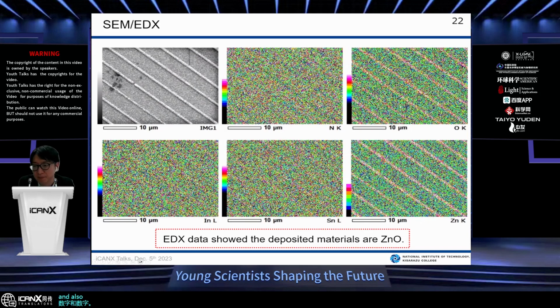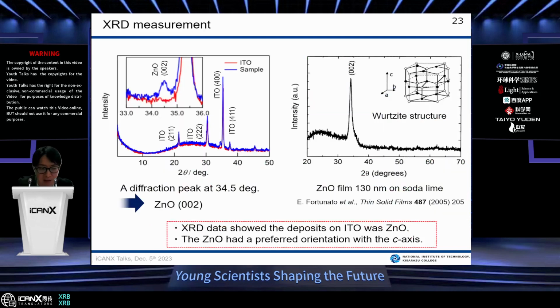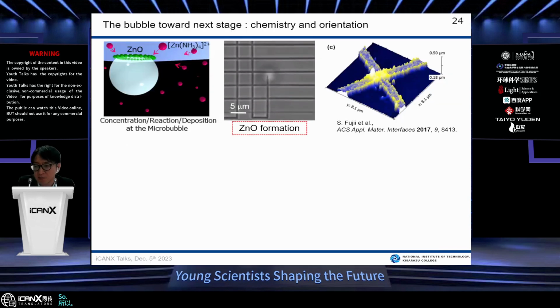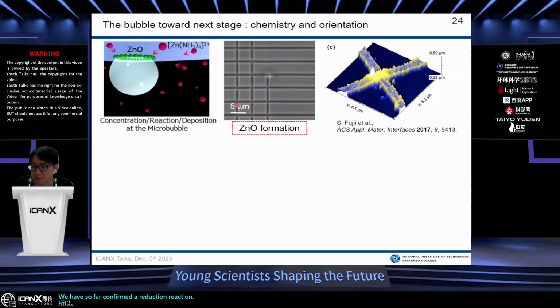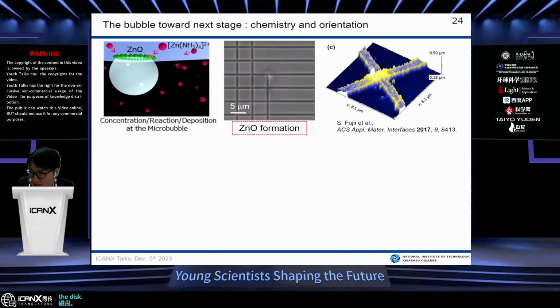XRD also supports the zinc oxide formation, like this small peak: zinc oxide 002 is the same peak at 34.5 degree. Also, compared to the previous report, zinc oxide had a preferred orientation with the c-axis perpendicular to the surface. So we have so far confirmed the reduction reaction and hydrothermal synthesis phenomena around the bubble, like this space.